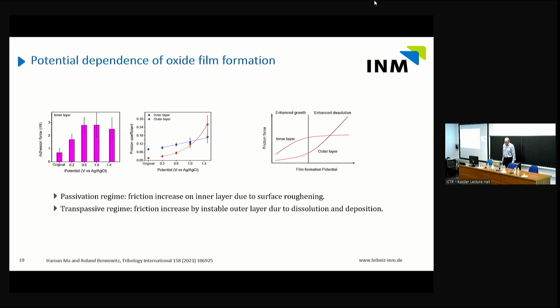initially. So be warned, if you do electrochemical anything on metallic glass, there is, of course, the oxidized surface, but there's also a lot of corrosion products just hanging at the surface, not really in the surface, on the surface, more like at the surface, I would say.